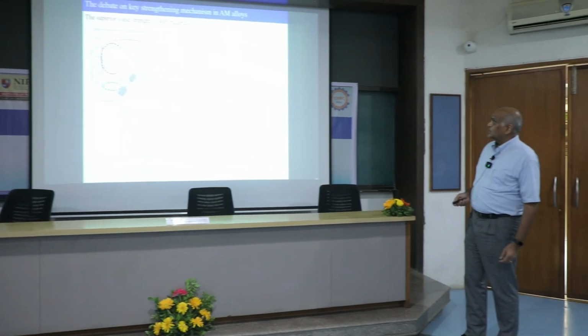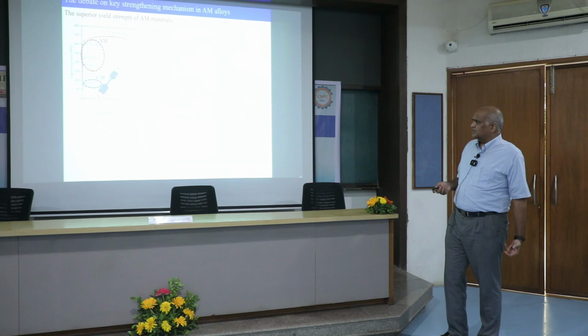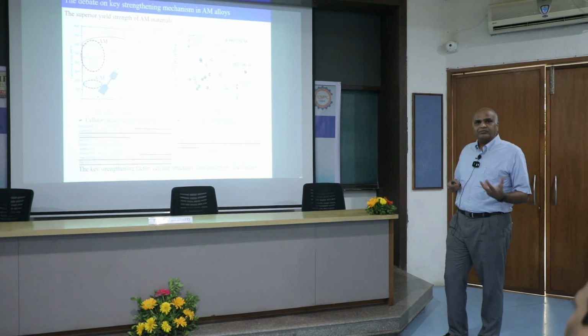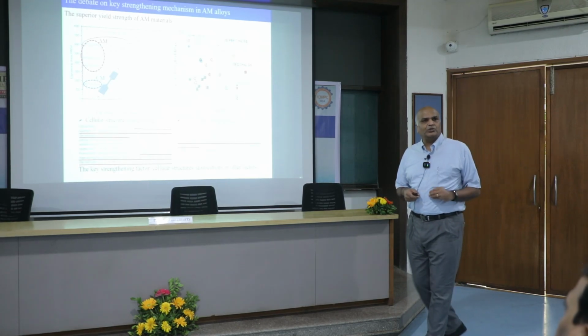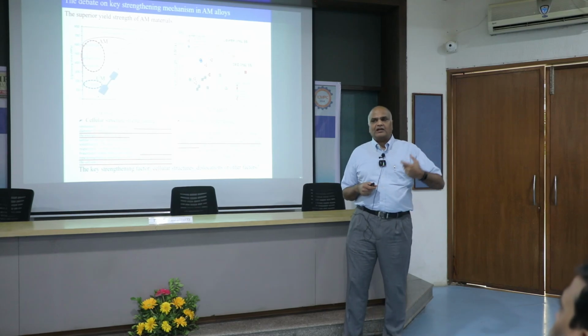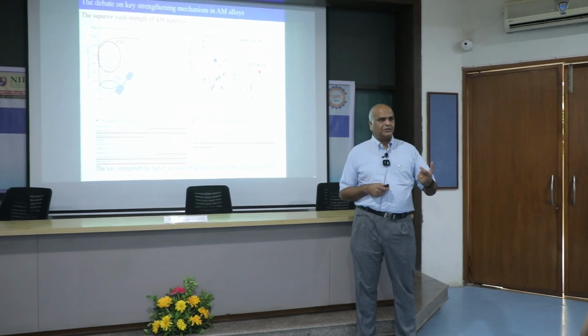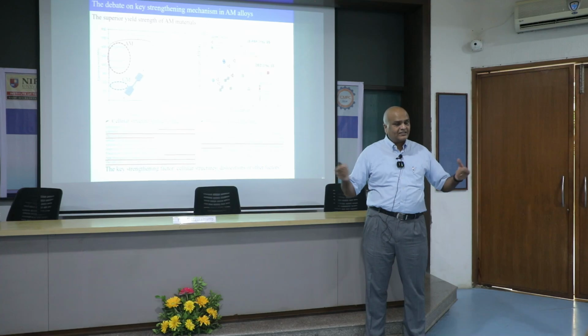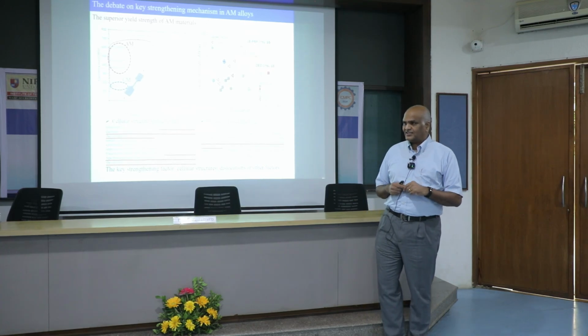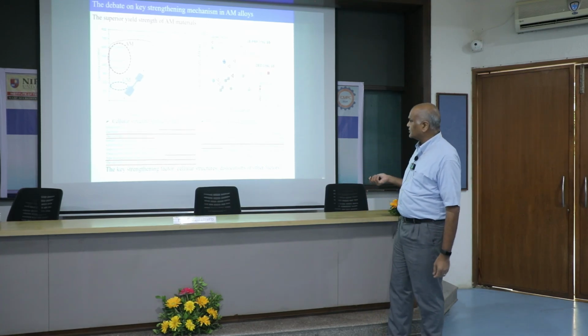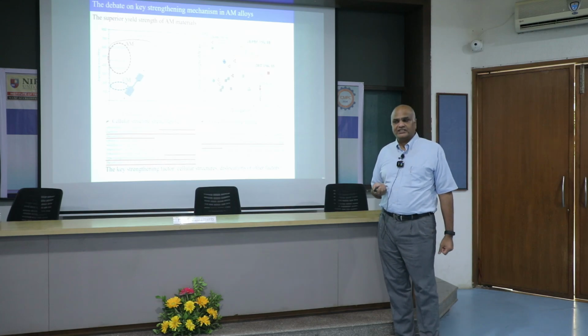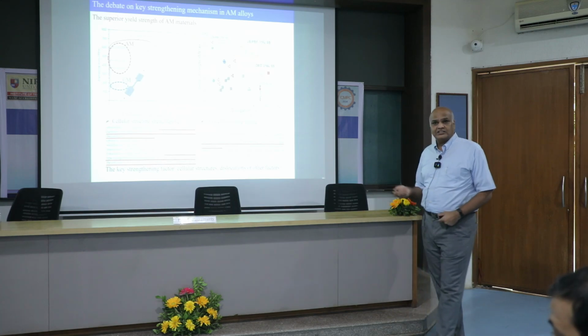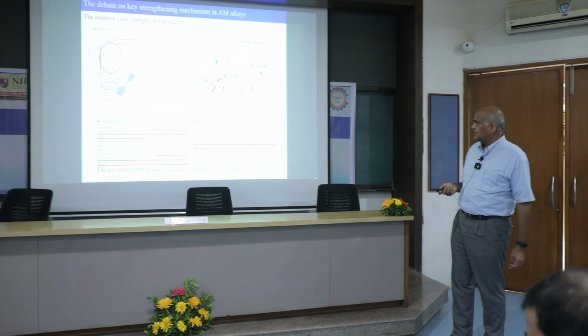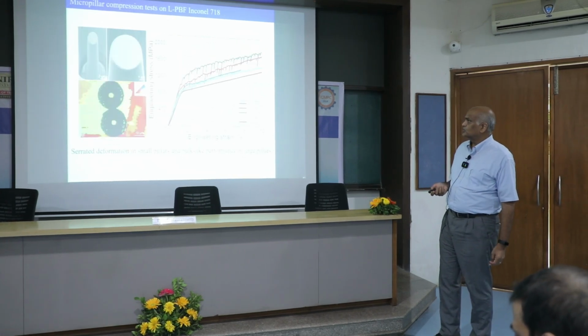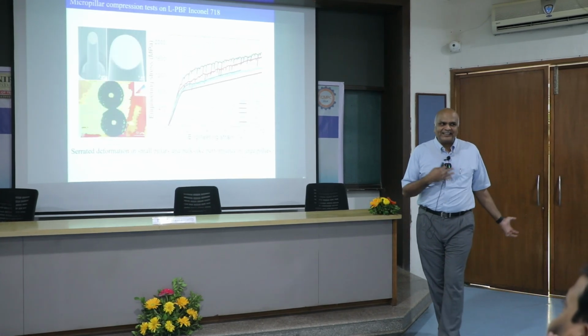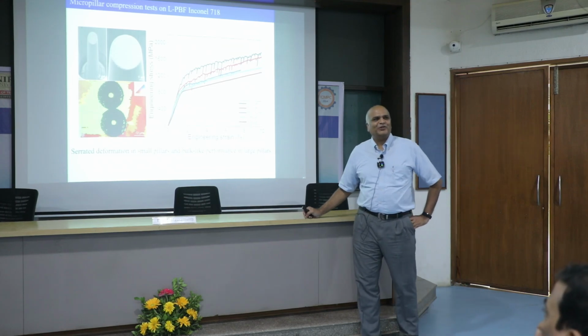Now, there are lots of debates about this. Some people say this is due to Hall-Petch, where you essentially have grain boundary strengthening, so the microstructure length scale changes, the cell size, and that is the reason. Some other people argue that it is because the dislocation cells have a higher dislocation density, and that causes the strength. To resolve this, now I'm getting quite deep into my own research.